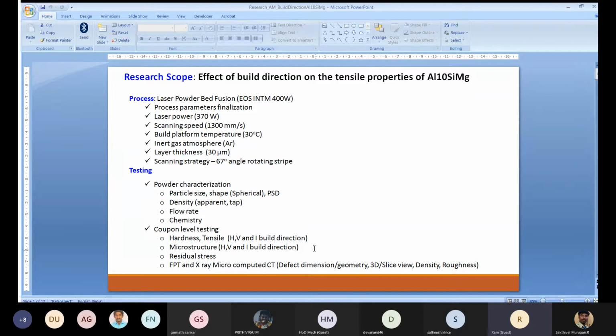And chemistry is very important. We ensure the input raw material chemical composition is similar to aluminium 10SiMg. Plus, we fix the amount of gaseous elements like oxygen, nitrogen and hydrogen there. Then we do coupon level tests like tensile and hardness tests for all the 3 directionally built samples, and microstructure also, residual stress also.